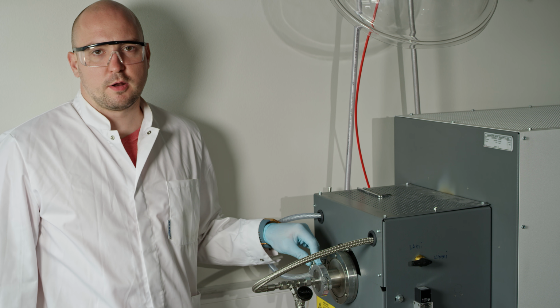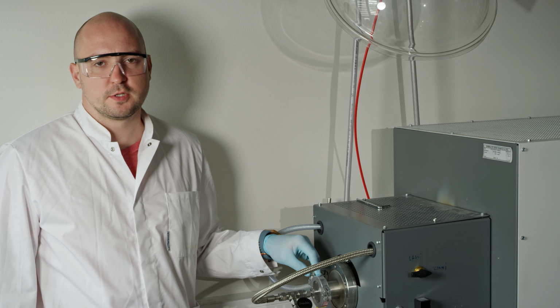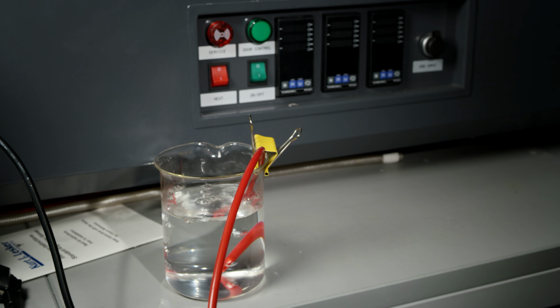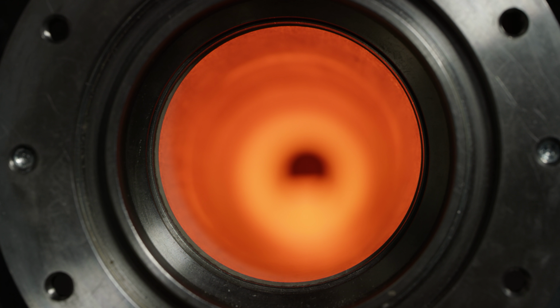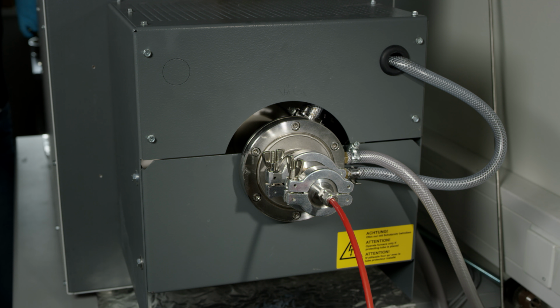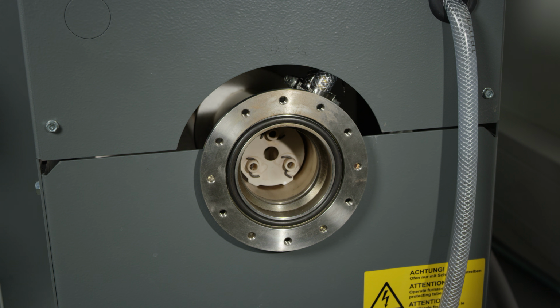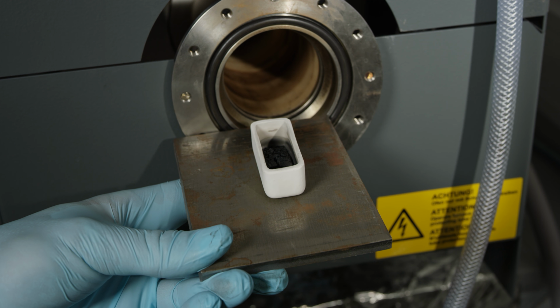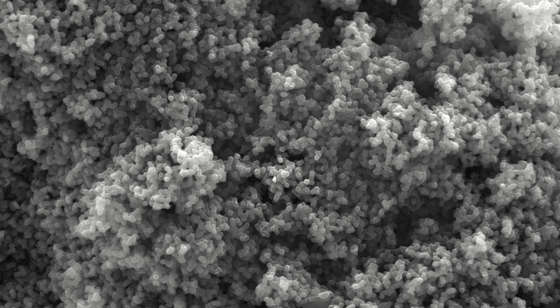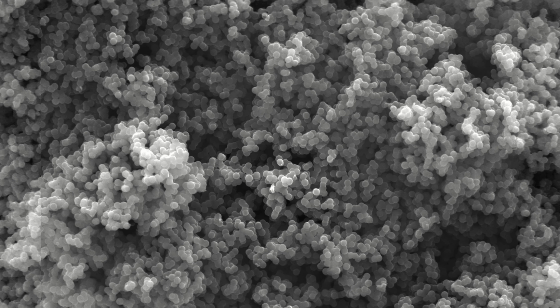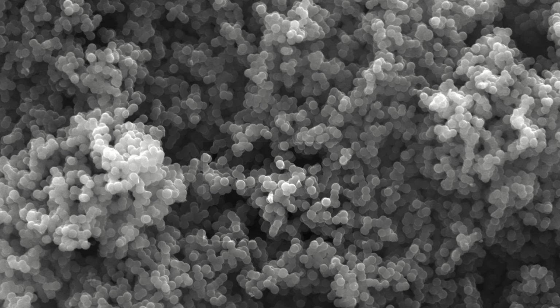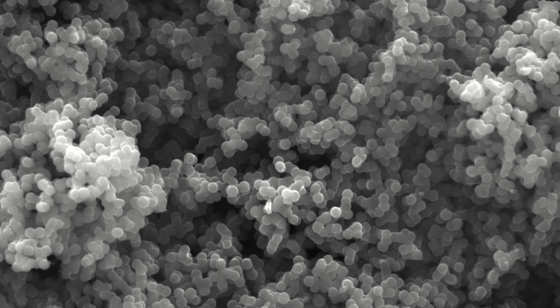Now we're ready to pyrolyze this carbon using this furnace, and we do it in argon atmosphere, so the material would not burn. In this process, all other elements are removed from the carbon structure and the carbon becomes further graphitized, which will create more sites for sodium adsorption. Here you can see scanning electron microscopy image of hard carbon material. These particles are spherical with a very narrow size distribution.